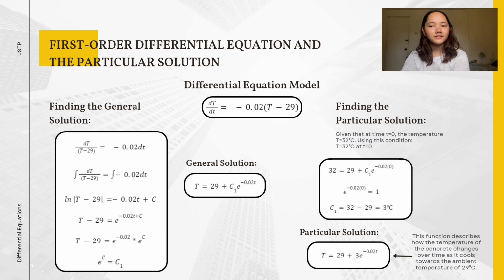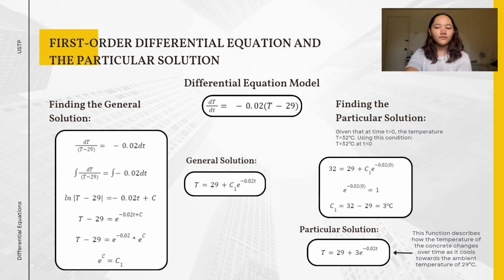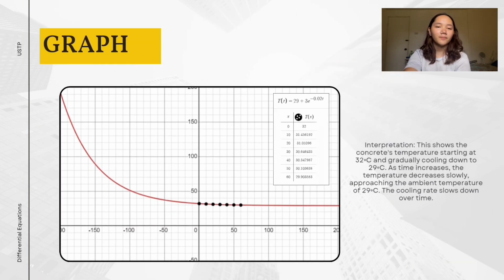Since we are given that at time 0 the temperature is 32 degrees Celsius, we use this condition. We input the values and it becomes 32 equals 29 plus c1 times e raised to negative 0.02 times 0. Since e raised to negative 0.02 times 0 is equal to 1, we multiply this to c1, making c1 equal to 32 minus 29, which is equivalent to 3 degrees Celsius. When finding the particular solution of the equation, we substitute c1, which is 3 degrees Celsius, into the general solution. Then, the particular solution is temperature equals 29 plus 3 times e raised to negative 0.02 times time. This function describes how the temperature of the concrete changes over time as it goes towards the ambient temperature of 29 degrees Celsius.